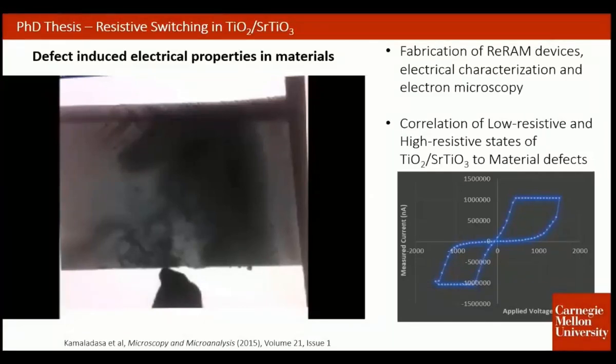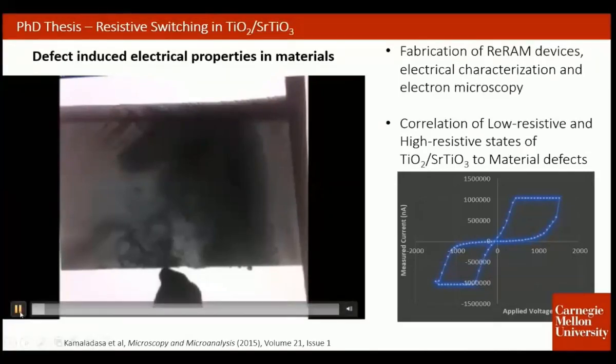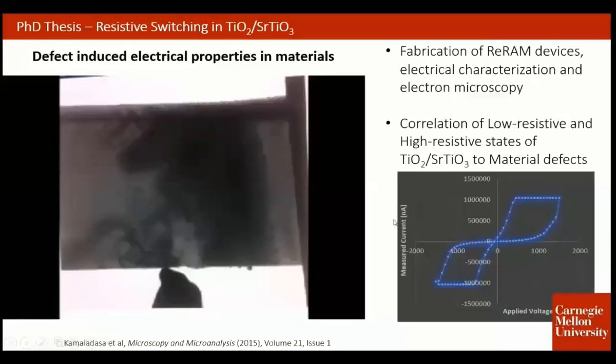In this experiment, I stressed the titanium oxide in a certain way, and we did it inside an electron microscope. We could see defects or networks of dislocations forming and decreasing in size. And we correlated that to the resistive state. So let me show you this video. This increase in this black portion, and that decrease in that black portion, is the increase and decrease of the dislocation density.